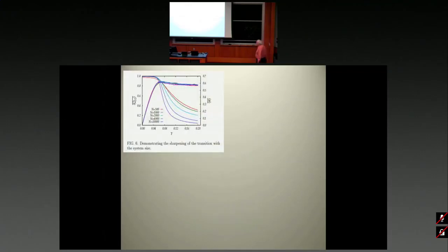And now you see you can measure the order parameter as a function of your strain. And that's a very crucial diagram. Because you see, this is the stress versus strain. You see this is where the yield is, roughly. And this is how the overlap looks. It starts at the order of 1, and then as a function of the system size, 500, 2,000, 4,000, 10,000, etc., you see that Q12 is going to 0 when gamma is increasing. The speed or the slope at which it is going to 0 is a function of the system size, and in the thermodynamic limit, we argue, it is going to be infinitely fast.